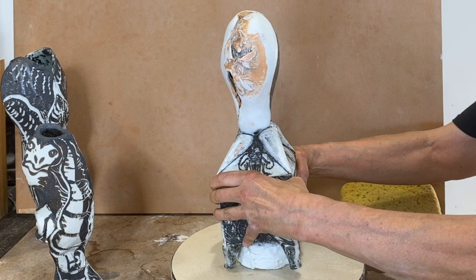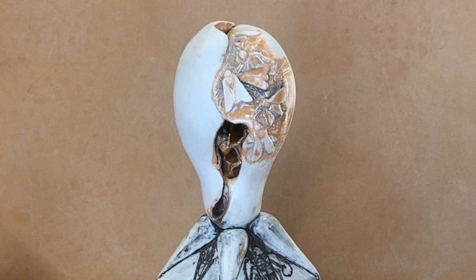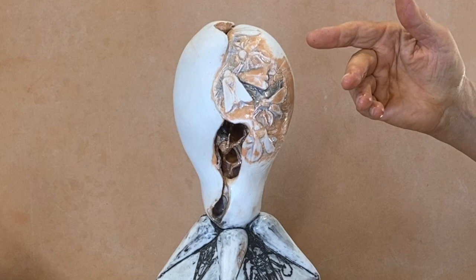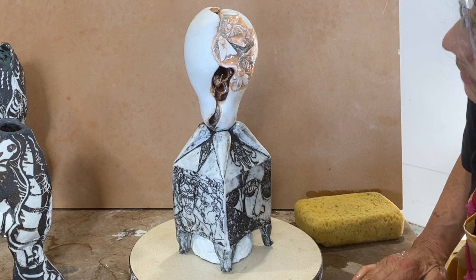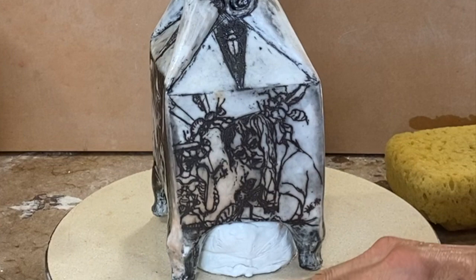When it was green, I poured a lot of copper-green slip on the inside, and you can see that it's kind of pink in there. And then it goes sort of black and blue up above, and it gives some nice dark lines inside on top of the insect's back. I think that was a nice effect — copper-green low-fire slip — and that pink comes from copper in reduction. Then when it was bisqued, I took my thinned-out shino and I poured it inside this honeycomb all the way through the top, down into the bottom, until it ran out the bottom hole of the piece, and I did that a number of times. Here on the side of this piece, down at the bottom left, you see that kind of sunset glow — that's the soda ash coming through.